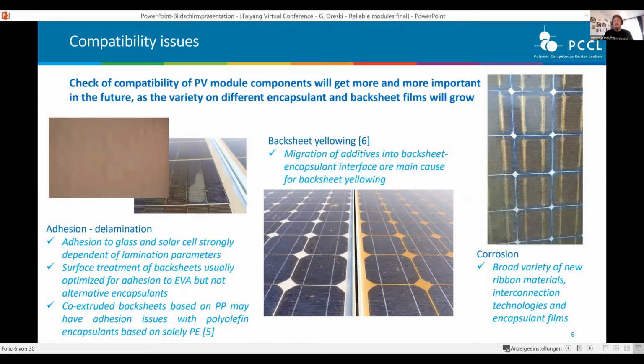For corrosion, we see a broad variety of new ribbon materials, interconnection technologies, and encapsulant films coming up. And sooner or later, we will also, unfortunately, have our surprises there, I guess, in the best or in the worst case. Yeah, and why is backsheet yellowing an issue? In most cases, backsheet yellowing is some sort of migration and then reaction of additives coming from encapsulant and backsheet meeting at the interface and causing this yellowing reaction. And also here, a proper design matching could avoid this kind of degradation mechanism.